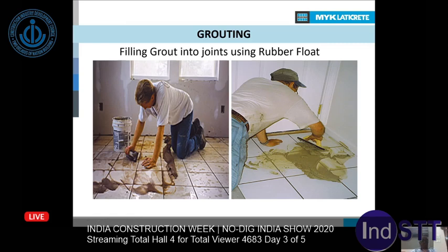And again, it's very, very important. Once you're done with the tile adhesive, then you go and fill the joints with a good material. Again, based on your application, you can go with the cementitious grouts. That's also factory made. But if your area is really high traffic or it's a very special area like high moisture, then we always recommend going with epoxy grouts. That's also a highly engineered material, factory made, it's highly durable, and it takes care of all the issues that come with the normal cement paste or other cementitious style grouts. So once you've done this, I think your installation is completely done in a good manner.